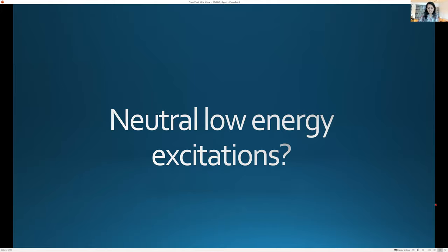The next possibility is that there is a viable possibility that maybe these oscillations are not associated with a Fermi surface, but they're just associated with electrons jumping across the gap at the Fermi energy. And so the other possibility is some kind of low energy excitations that exist that somehow couple to a magnetic field, but don't have any signatures in the electrical conduction, which is of course the conundrum. I am not sure there is a clear answer about how to get this, especially quantitatively. There are proposals which we can talk about, and I think they come down to a question of at which order do they couple to the magnetic field, at which order do they couple to the electric field.